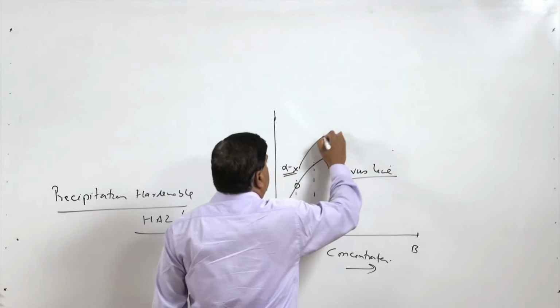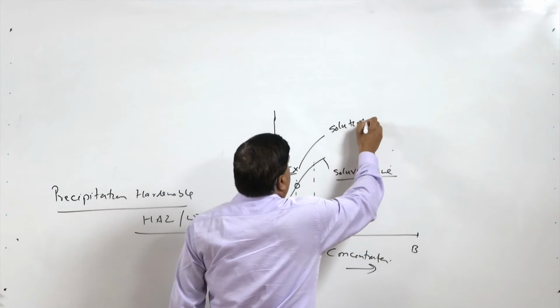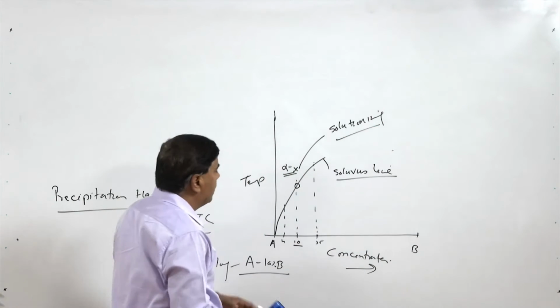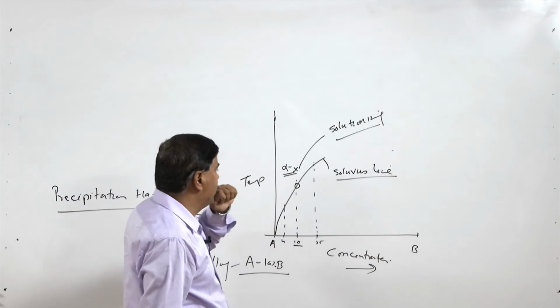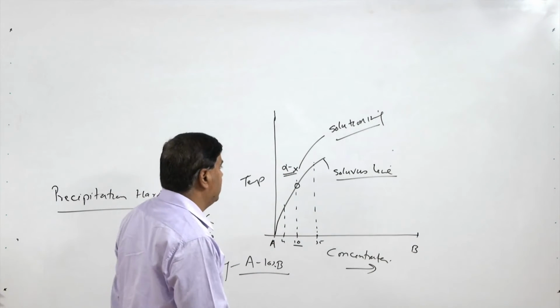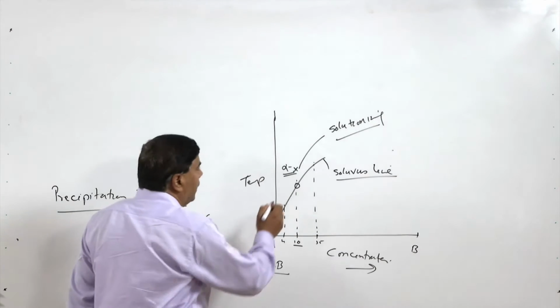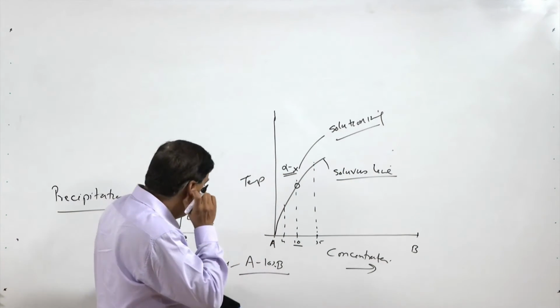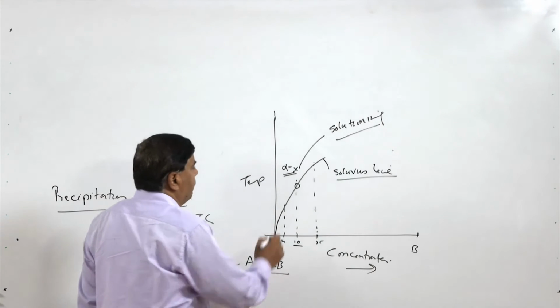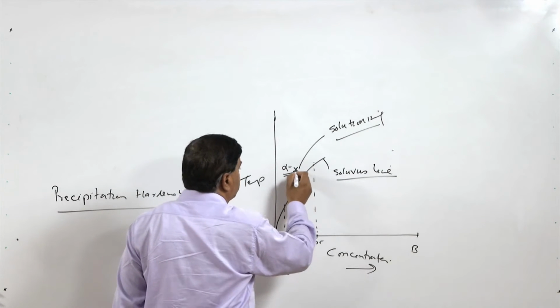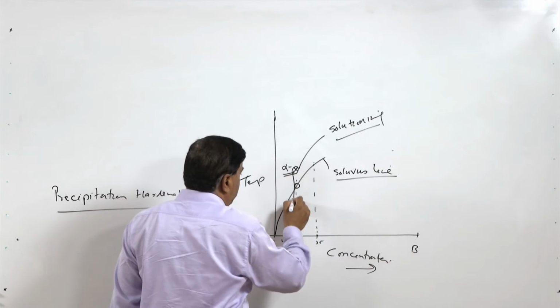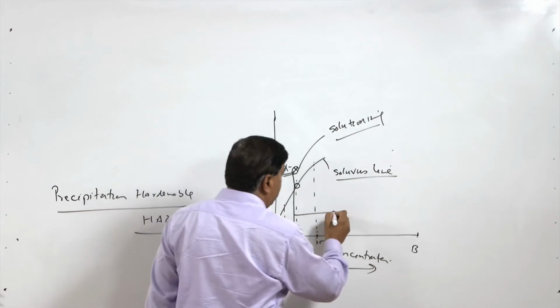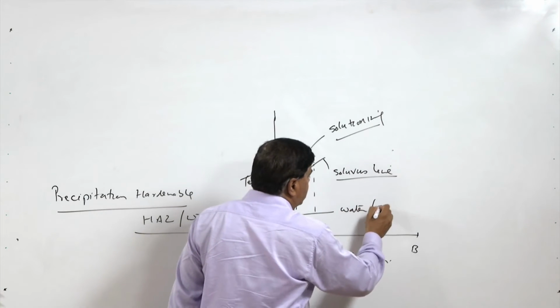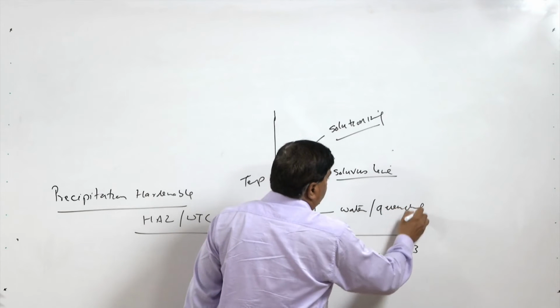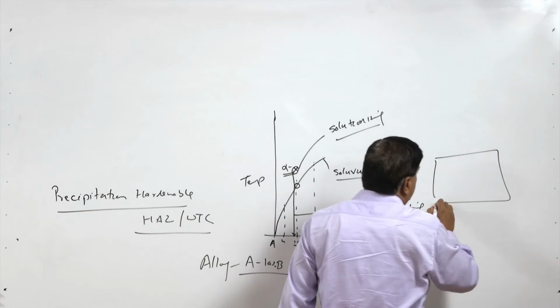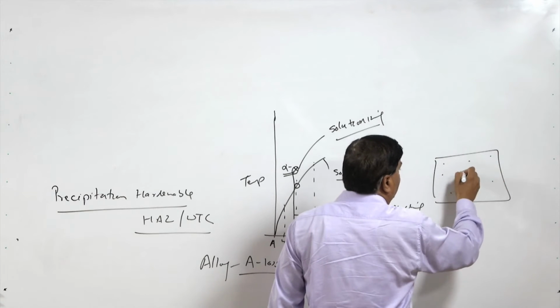So, this one is called solutionizing. Heating at the temperature above the solvus line helps to achieve the homogeneous solid solution. This step is called solutionizing, and then once the homogeneous solid solution of the alloy is formed, we will be quenching it fast. So, it is quenched by cooling rapidly in water or oil. This is called quenching.